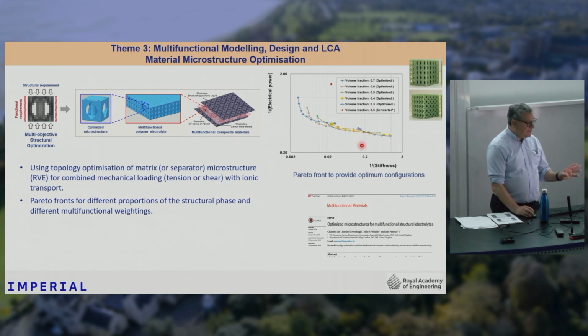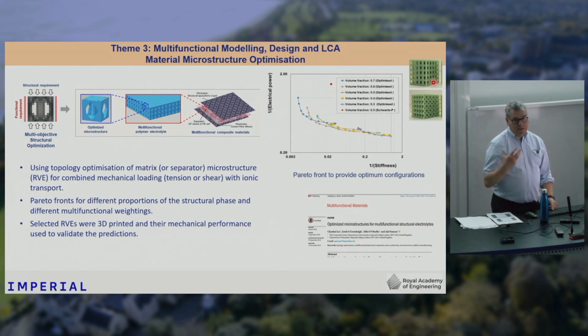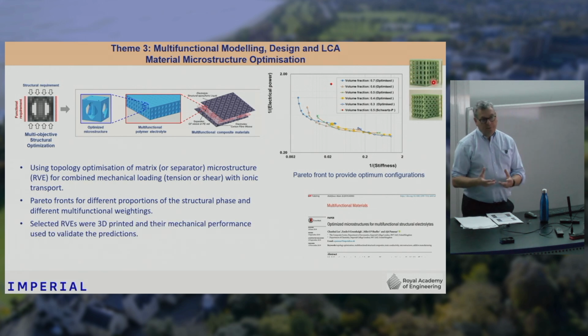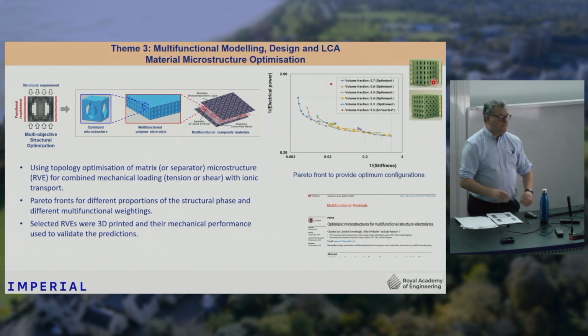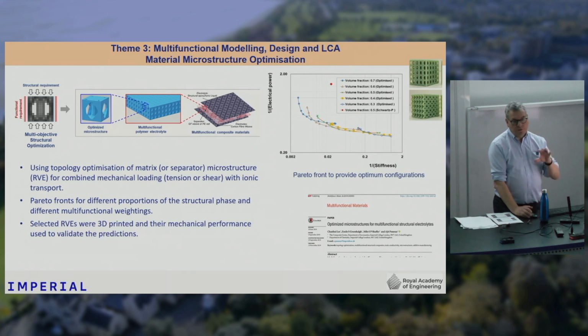Now, what I thought was really exciting about this was once we'd done the topology optimization and come up with these solutions, we 3D printed them, as shown here. And we then characterized those in the lab. We looked at the mechanical properties and the electrochemical properties, albeit at a much larger scale. So these solutions were scale independent, and we were not really capturing some of the micro scale physics that could happen. And that allowed us to demonstrate that these solutions were credible.